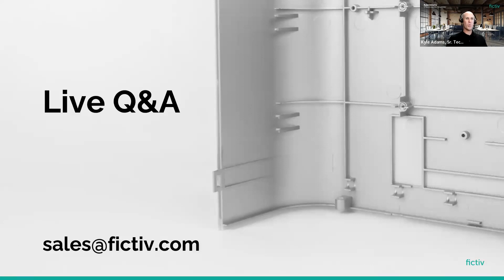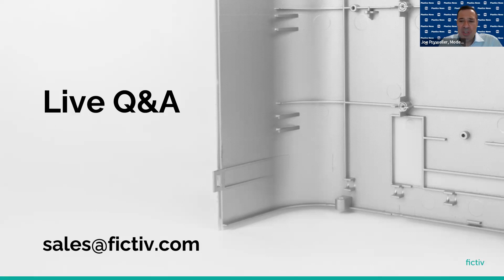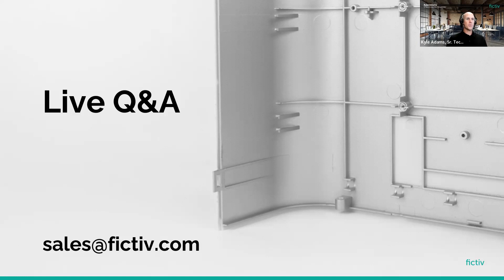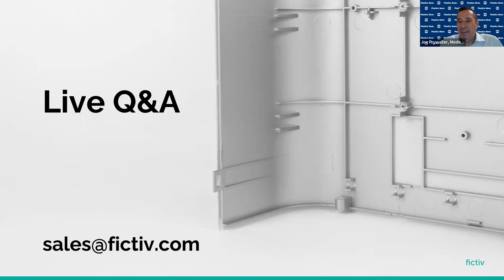Q&A: Recycled materials can technically be used, but FICTIV generally avoids them. Reprocessing a material degrades it — grinding and re-running material through the press reduces its properties, potentially affecting chemical compatibility. Mechanical interlocks become even more critical if recycled materials are used. That said, there's no fundamental reason you couldn't use recycled materials.